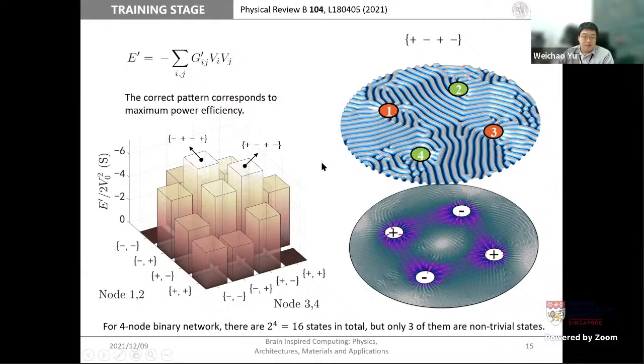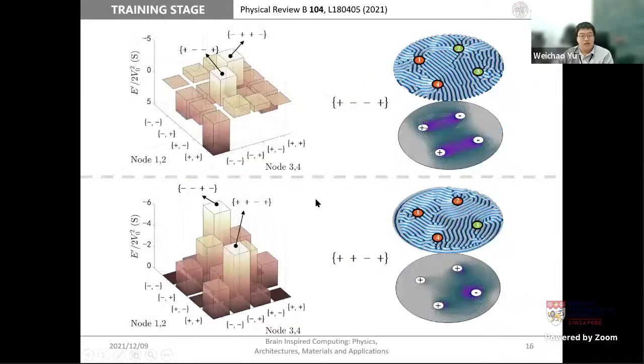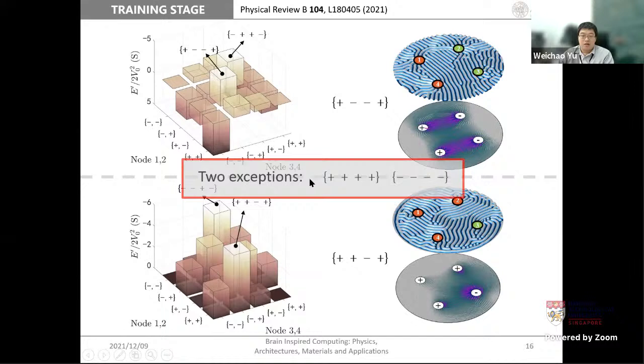So for a 4-node binary network, we have a total of 16 different inputs. But according to the symmetry of the patterns, we have only 3 non-trivial states, and this is 1. And here I plot the remaining 2 non-trivial states. So we can see that for arbitrary input, the texture can finally adjust itself so that the inputs become the ground state of the 4-node Hopfield network. However, there are two exceptions. When all the input voltages are positive or all negative, there will be no voltage difference and no current flowing through the magnetic film, so the training cannot be performed.